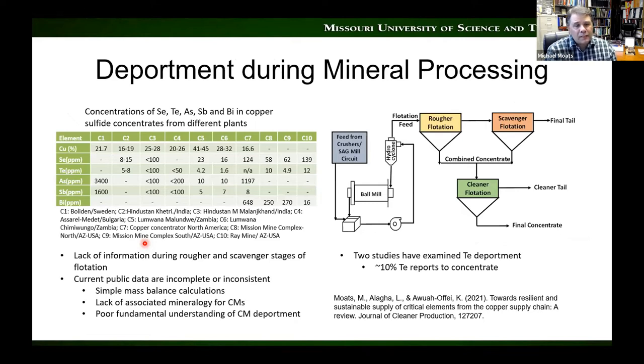When we look at the mineral processing, when we go through comminution and flotation, flotation, of course, is where we make the separation. When we look at the concentrates, there's a wonderful report back in the early 1980s, where the U.S. Bureau of Mines went through and characterized the tellurium content, selenium content, and a host of concentrates produced in the United States. Of course, most of those mines are now shut down. So when we went through and looked at more recent data, again, the amount of concentrate data is minimal. You're always wondering about grab samples. How accurate is this really from a day in and day out?